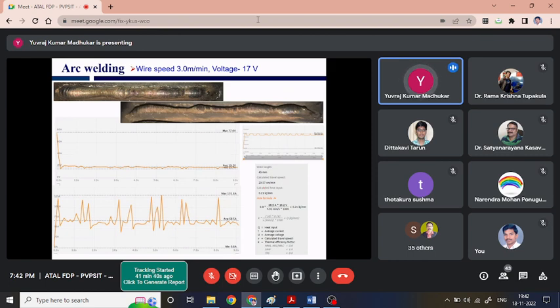Now, if we talk specifically about the MIG-based additive manufacturing process, MIG is nothing but a constant voltage process, and the current is determined based on the resistance between the electrode and the workpiece. Look at one case when wire feed speed is, let us suppose, 3 meters per minute, and the commanded voltage is, let us suppose, 17 volts. We are getting the deposited bead something like this. The bead is here more, here again lesser, here more, again lesser, again more, so we are not getting a consistent, very good deposited bead.